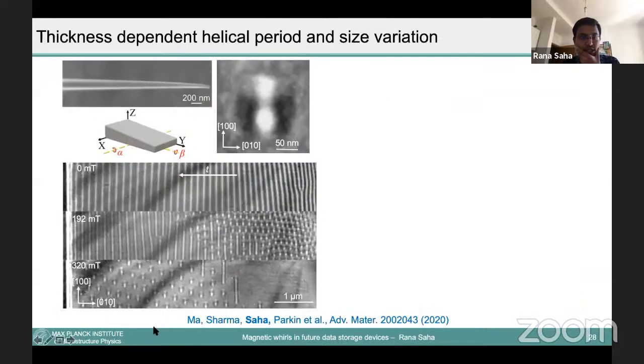So this skyrmion is also possible. You can tune the size of the skyrmion. As I mentioned, instead of 20 skyrmions, if you can have 2000 skyrmions, you have more data density. So you increase the density, but you have to have some kind of stability.